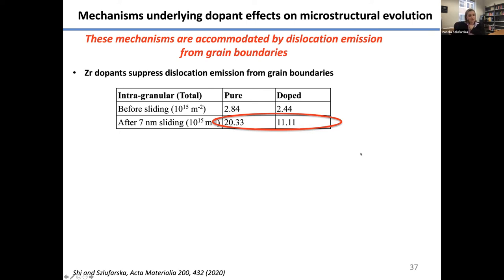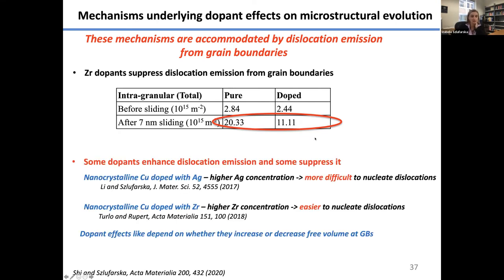So the interesting question is whether it's always true that the dopants will do that. Is it always true that the dopants will suppress dislocation emission and suppress grain growth? And the answer is that it's not. We looked at the literature and our earlier simulations, and we found that whether dopants increase or suppress dislocation emission, and therefore the microstructural evolution, depends on the dopants.